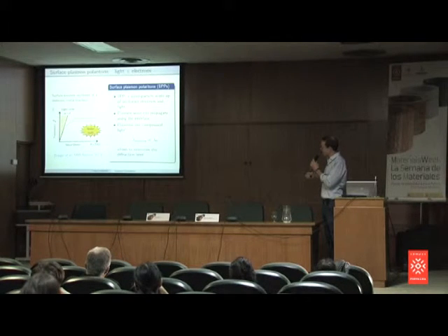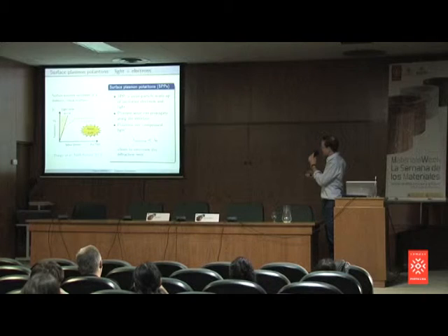It has a wave vector like this, go down from this line. And the yellow curve here is the dispersion for a plasmon in a conventional metal. So you see, you come in with a frequency, and the dispersion of the plasmon is way to the right of the light cone. Means higher momenta, means shorter wavelength, and we are here.